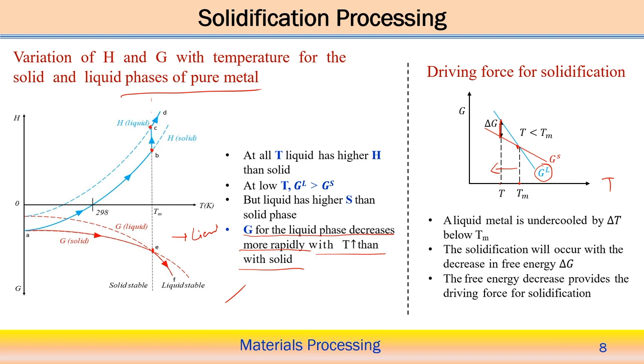So, a liquid metal is undercooled. Here the temperature difference, delta T, is basically Tm minus T. This is the degree of undercooling available here. I mean to say that the greater the degree of undercooling, the greater delta G, the change of the Gibbs energy, is also. So, it means that a higher degree of undercooling is the most feasible condition to start the nucleation process during the solidification of a pure metal. So, therefore, more undercooling means more change of the Gibbs free energy.